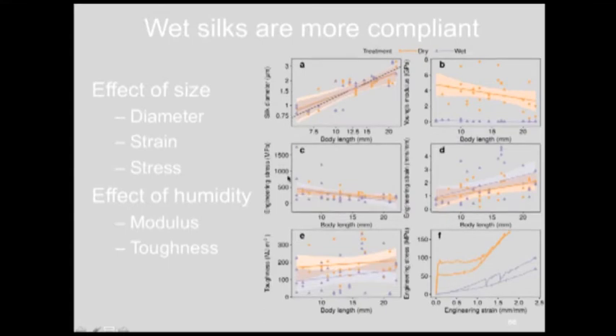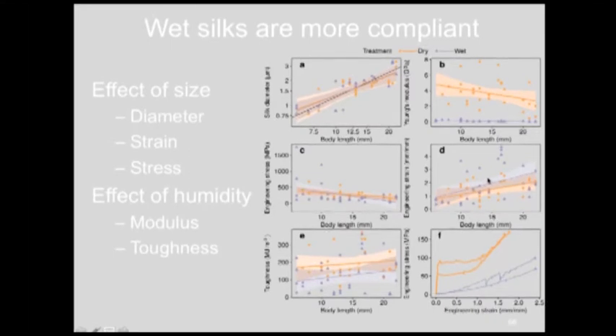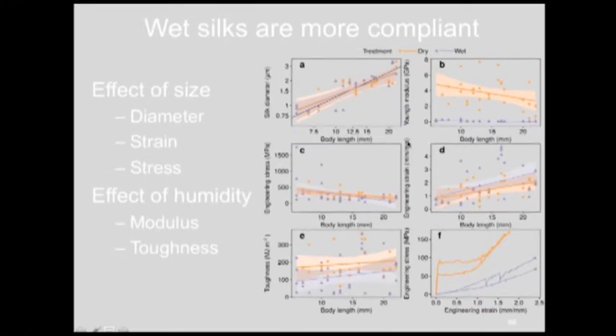However, if we compare between our treatments, between wet and dry humidity conditions, we do see that our stiffness is very different, that in wet conditions, it becomes very compliant, much like a rubber band, as I had said, but in dry conditions, quite stiff. And that's quite easily identified here in our mechanical behavior graph, where we can see initially when you stretch it, the dry fibers are quite stiff, whereas when they're wet, they're very compliant. And this has big implications for our adhesive tests, as I'll show you in a second, because this initial area is under the same forces that adhesion occurs under, which would obviously allow for those forces to potentially be dissipated.